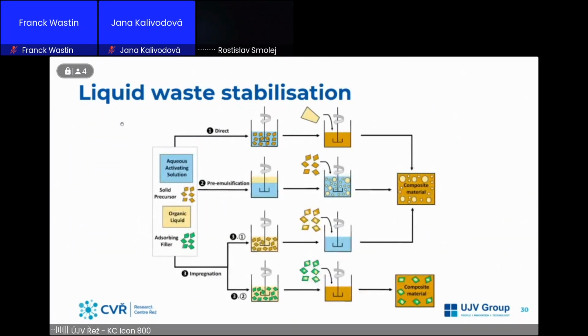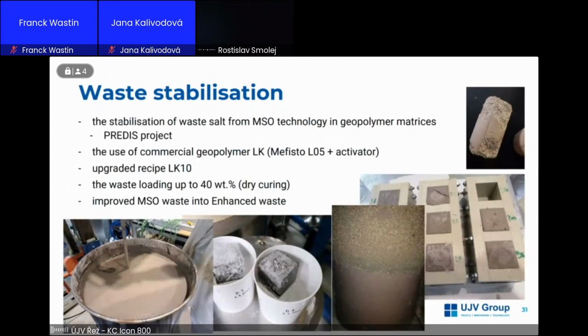In our lab, we are mainly focused on the geopolymer matrices. And this is, for example, the liquid waste stabilization, which was done in the previous project. It's not very common, but if you don't want to put your liquid waste, for example, the oils, into the molten salt oxidation, you can try to put them directly into the geopolymer matrix. We had quite good results. Well, not as good as if you put it through the molten salt oxidation, but still, it wasn't that bad, actually.